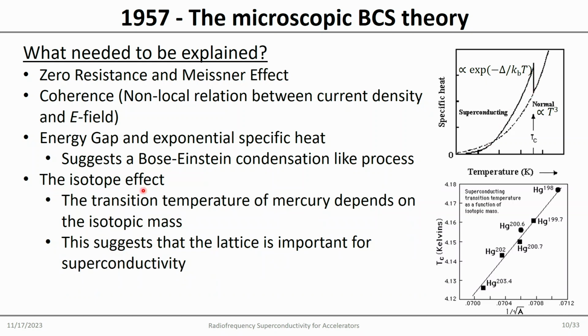Then also what's interesting, there was something called an isotope effect. So this is a transition temperature. It's basically the temperature where mercury becomes superconducting, and it's a function of the mass. If you have very heavy isotopes, or very light ones, the good thing about mercury is that it has several stable isotopes, so you could really do that experiment. And you see how well: the lower the average isotope mass is, the higher the transition temperature.